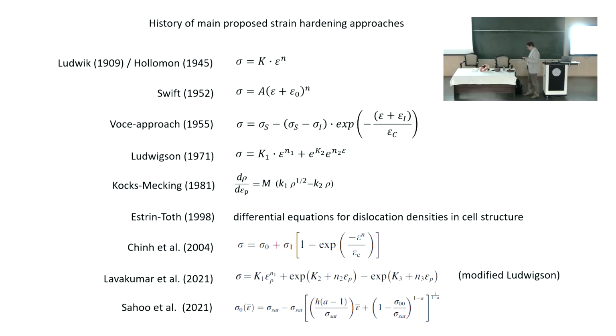So the modeling we made in 1998 is written in terms of differential equations for dislocation density variations in the two phases, the dislocation cell wall and cell interior. Then making a simple composite model, one can go to the macroscopic level, and very nice results can be obtained. Plenty of results come, not only the macroscopic stress-strain curve reproduced, but also dislocation density variations.